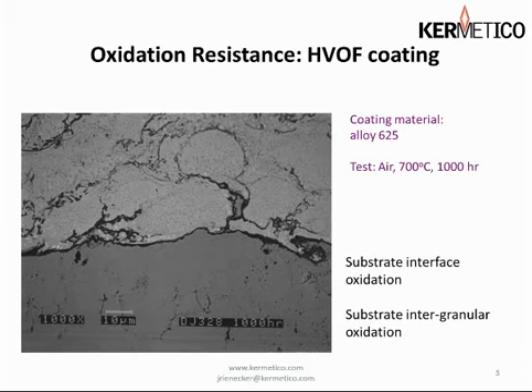Then there's the difference in oxidation resistance between an HVOF coating and our HVAF coating. This is a photomicrograph of an HVOF coating, alloy 625, after a 700 degree Celsius test in air for 1,000 hours. You can see a number of things which are not desirable: substrate oxidation, oxidation between the particles in the coating, and intergranular oxidation in the substrate.